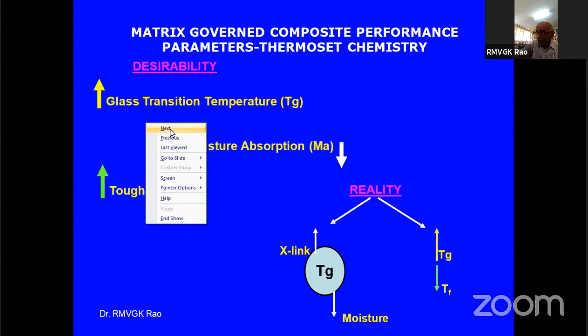So the TG and toughness are at loggerheads. One of my colleagues has actually worked on high temperature polyimides, modified with epoxies. It is what's called interpenetrating network polymers, IPN. That's a very good solution where you can increase the TG at the same time, not sacrificing too much on toughness. Okay. Now, what is this TG?